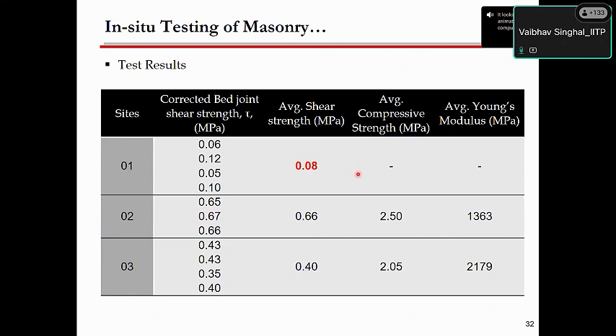This is one of the tests we have done for about 10-15 buildings. I'm just showing you results of 3 buildings. In one of the buildings, we found that the shear strength is very, very low, 0.08. And if you remember, I gave you a number of 0.1 as per IS 15988. We also did a detailed assessment, and we found that this building was unsafe for resisting earthquake forces. Whereas for the other 2 buildings, the shear strength was quite good, 0.66 and 0.4. We were also able to find out the average compressive strength, 2.5 and 2 MPa, and the modulus. So this is what you can get from all these tests.